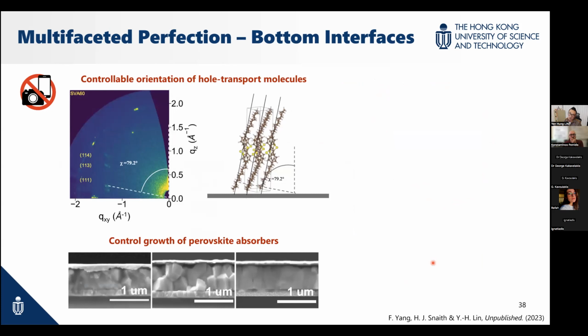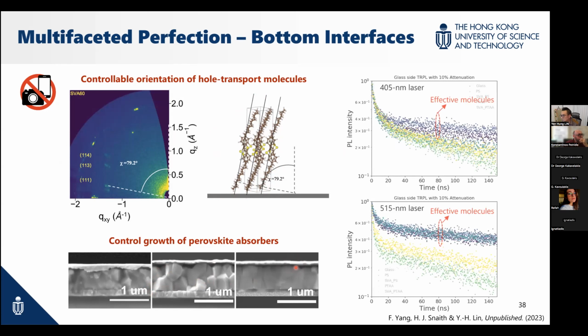But something interesting we found is that with this approach, we can align the molecules in a way that is either face-on or edge-on, and depending on these conditions, it further affects the formation of perovskite. So we did a little bit of study using TRPL. Actually, I labeled things wrong here. I'm sorry about this. I took the wrong figures. So the first one is actually illuminated from the upper side. The second one is illuminated from the glass side.